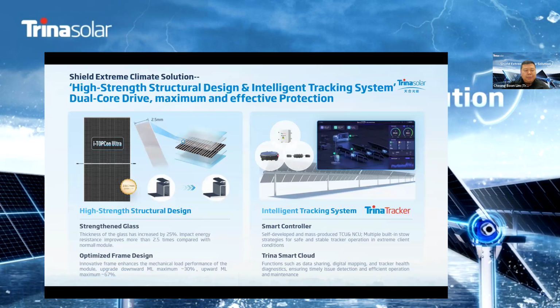So what have we done to our Trina modules and the overall solution that we are proposing to mitigate these extreme climate conditions? On the left, you can see we have increased the thickness of the glass by approximately 25%. This has helped to improve the impact resistance by more than 2.5 times compared to the normal module.